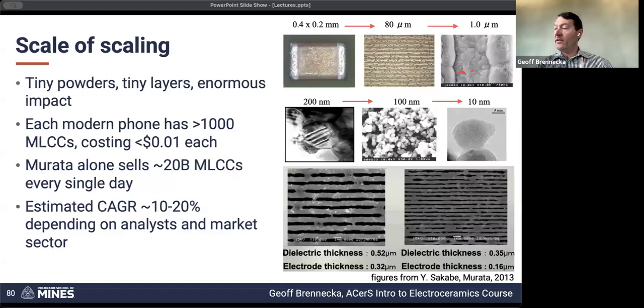And the reason for that is, as we'll get to later on, if you think back a little bit to the defect chemistry that we were talking about, if you have any charge defects at all, and you apply a field, they're going to move under that field. And so putting grain boundaries in the way will slow down that mobility and increase reliability. So a general rule is at least 3, 10 is even better, grain boundaries between the electrodes is a good target.